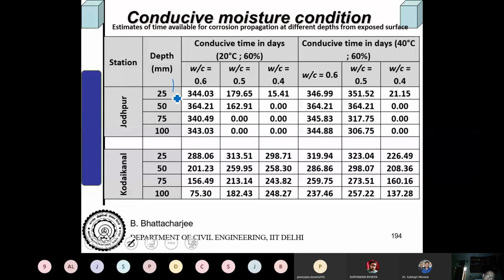And you can get the carbonation depth. For carbonation depth 100, the conducive days for carbonation is much higher with 0.6 water cement ratio, 0.5 if you provide 100. So in fact, actually you can obtain the cover depth. If you provide cover depth up to let's say 50 in water cement ratio 0.6, then you have a problem. But if you provide 0.5 water cement ratio, 162 days carbonation will occur. 0.4, no days carbonation.